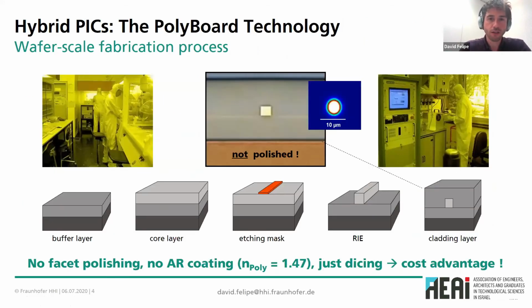And this schematic shows how these waveguides can be fabricated. It's a fairly simple process. That's one of the potentials of this technology, which is simple and therefore can eventually be low cost. We start with a silicon substrate, which is the darkest block here on this left-hand side picture, and we coat it with the bottom cladding, which has a specific refractive index. Then on top of it, we spin coat the core material, which will basically structure our waveguide, which has a slightly higher refractive index than the buffer layer.